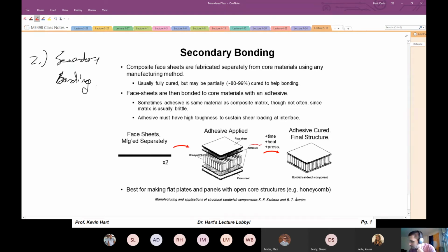And then the adhesives that are used to bond the composites to the honeycomb are generally lower strength, more ductility, have a little bit more malleability to them so they can absorb energy at the interface when you have, let's say, fracture that propagates between the face sheet and the honeycomb. All right, so a lot higher energy, a lot higher G1C values for the adhesive between the face sheets and the honeycomb.